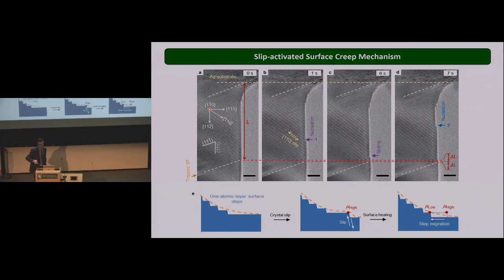Right? So one of the last slides I want to show here is that we came up with a mechanism to explain this behavior. And so the question is, does crystal slip come before diffusion, or is diffusion causing crystal slip? Because that's important to know. In general, diffusion can promote defects and dislocations. It's possible from grain boundaries. But the opposite was never observed.